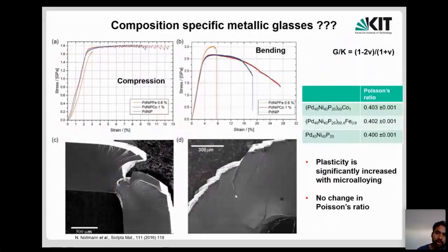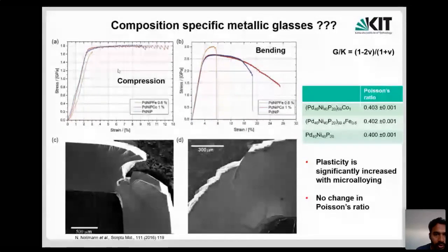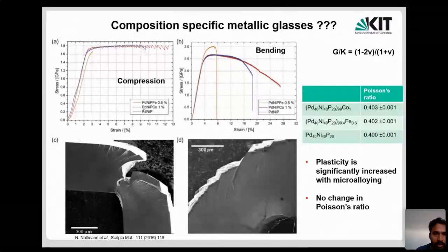However, recently another group also showed that this is not necessarily true. You need not change the Poisson's ratio. So they microalloyed the sample of palladium nickel phosphorus with iron and cobalt. And you see that the Poisson's ratio is essentially changing only in the third decimal. So there's almost no change. However, the compression and bending behavior of these compositions differ. The palladium nickel phosphorus shows a lot of ductility. Then the palladium nickel phosphorus cobalt also showed a lot of ductility, whereas palladium nickel phosphorus iron showed absolutely no ductility. So without changing the Poisson's ratio, you can also change the compression properties. So that composition specific nature is being debated here.